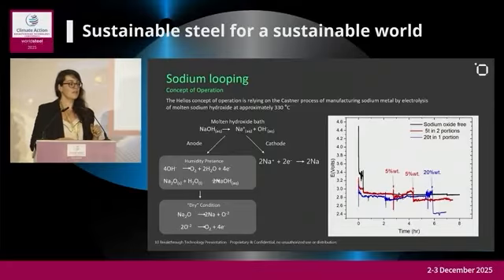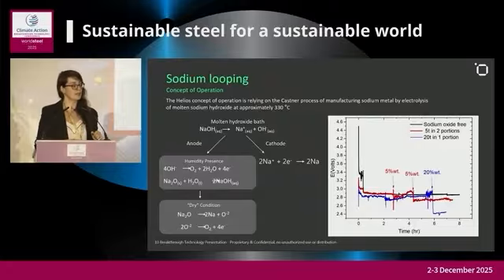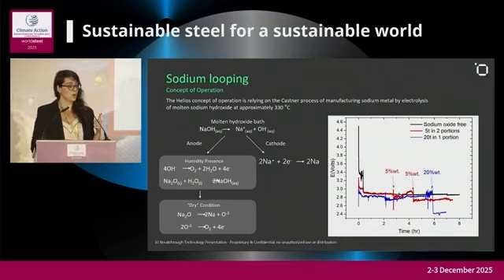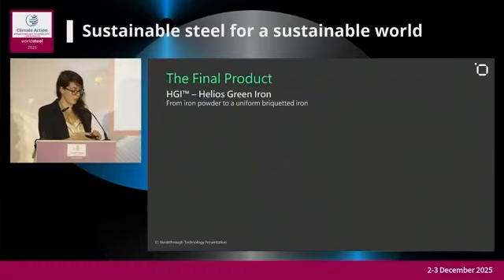You can see in the figure on the right that by adding the sodium oxide, which is from the separation train, we are lowering the potential. And by lowering the potential, it means, in other words, that we are at the level of voltage of the oxygen evolution. So this is the sodium looping.